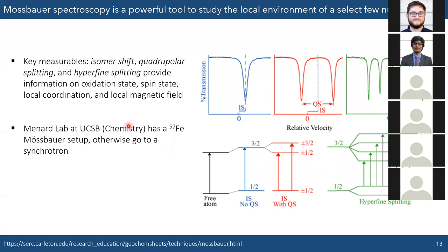And so with Mössbauer, there's really these three main measurables: your isomer shift, quadrupolar splitting, and hyperfine splitting. And these can all give you really powerful information on the oxidation state, spin state, local coordination, and local magnetic field.